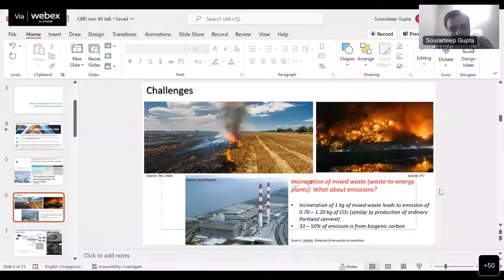So we need to develop some other material formulation, or rather an approach whereby we can use this kind of bio-based materials as additives to reduce the consumption of CO2 intensive binders. So I'm sharing with you a schematic, and that is something that has driven my research for the past few years on carbon capture and sequestration. For example, the CO2 that is emitted from incinerator plants or even from cement manufacturing can actually be captured, although there are certain challenges. For example, how do we get rid of the SOx and NOx, like SO2 and NO2, and really have high purity CO2 that we can capture? And the captured CO2 can be used to cure the concrete blocks, or rather the prefabricated concrete blocks.